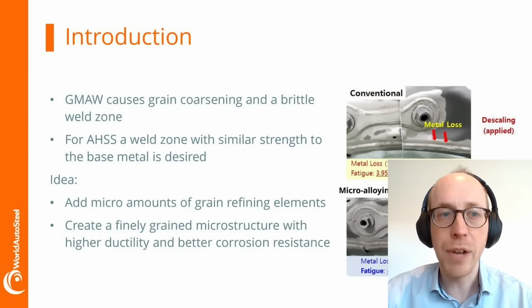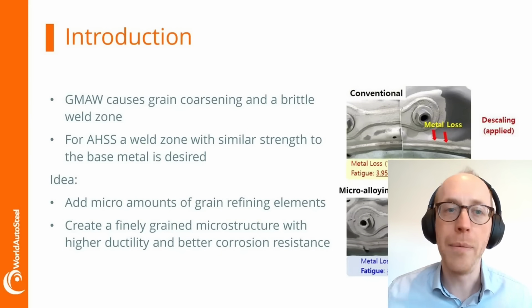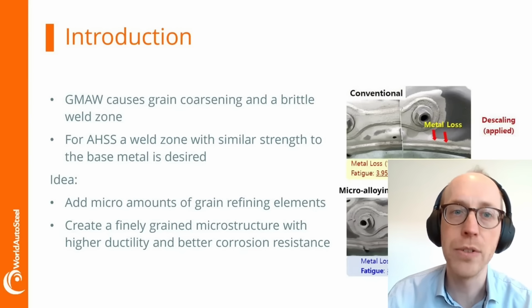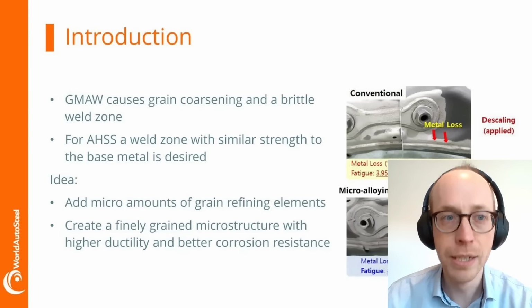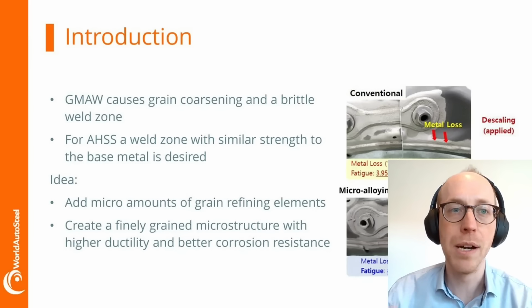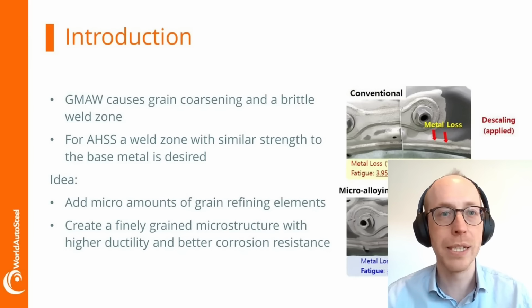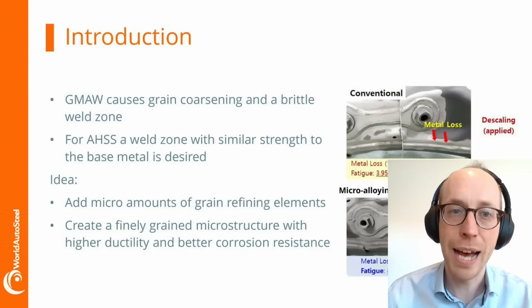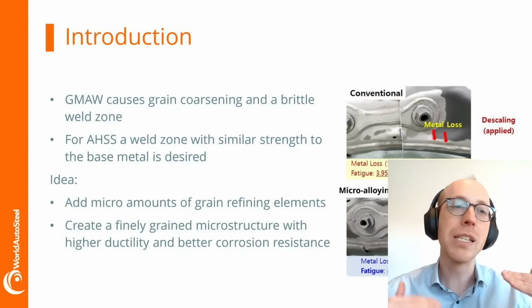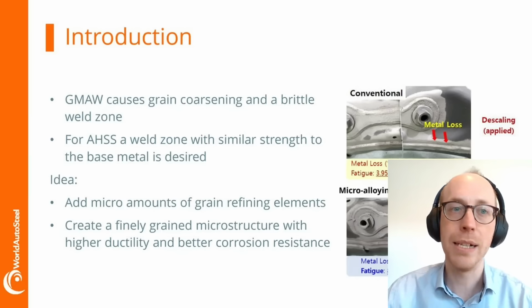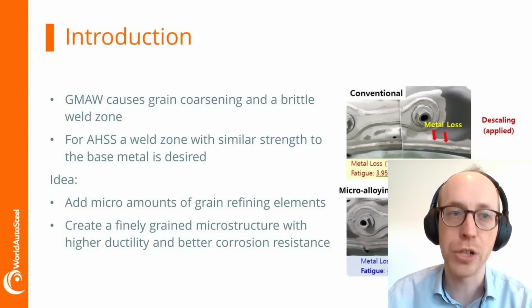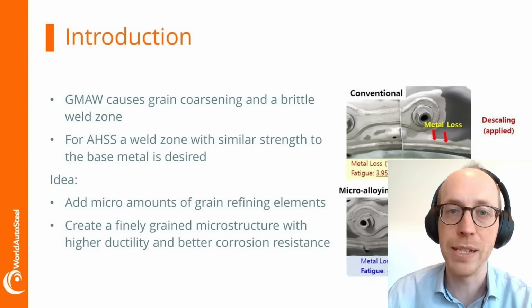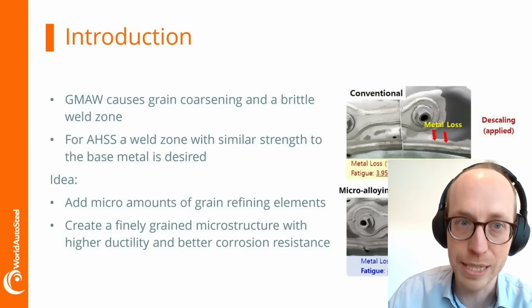If you want to weld advanced high strength steels, a weld zone with a similar strength to the base material is desired. This problem gets even larger if you're welding a steel with a higher strength class, because then the difference between the steel substrate and the weld zone will get progressively larger with the strength of the steel.